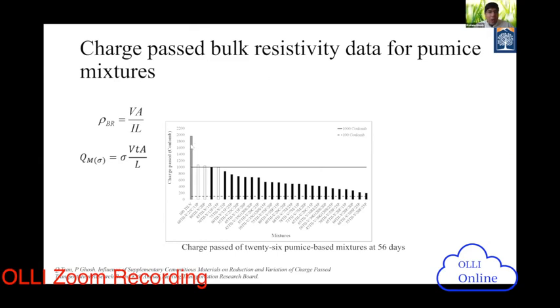The first one is the original control, meaning 100% Portland Type I. Now you see the graph starts to reduce. Most of the binary and ternary mixes are showing much less charge passed. How low? You see some of them. We talked about 100 to 1000. That's our aim in between. So almost all of the binary mixes got very little charge passed.